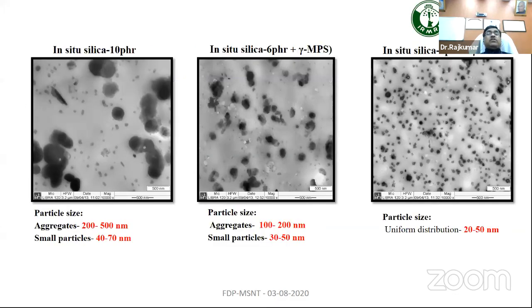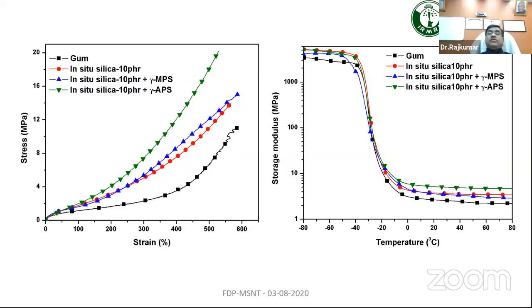For example, when you modify the silica using MPS and APS at 10 phr, the dispersion becomes very good in terms of morphology fixation. So modification with siloxanes leads to better dispersion. These are some of the surface modification chemistries people can take, and more research needs to be done on just modifying the surface.